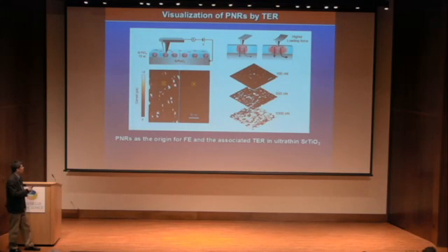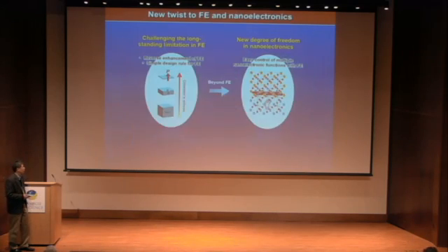And then also we increase the loading force and increase the area of the down polarization region. You can see that the conducting region spreads bigger and bigger, not homogeneously, but you can see the switching of large area nanopolar regions by mechanical writing.